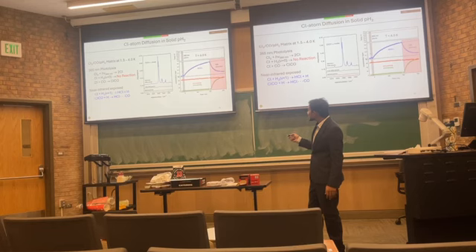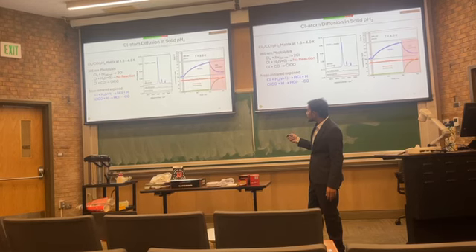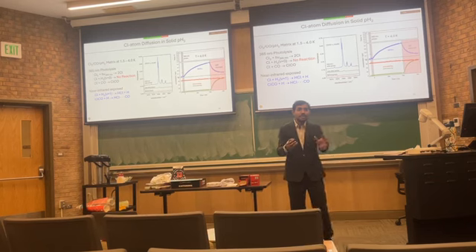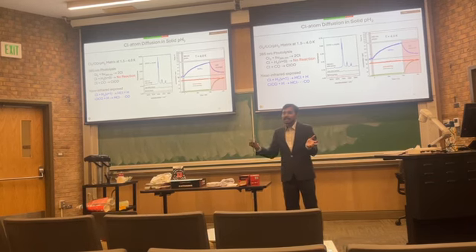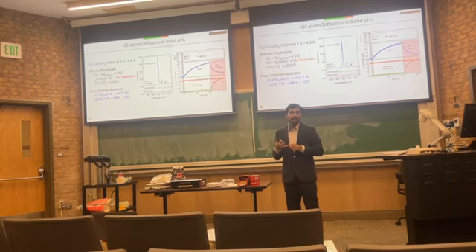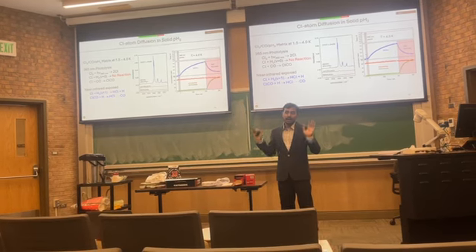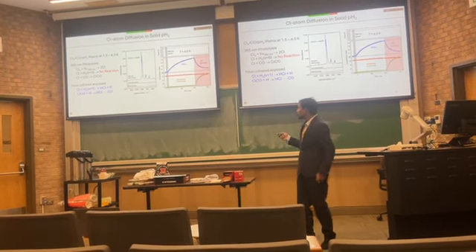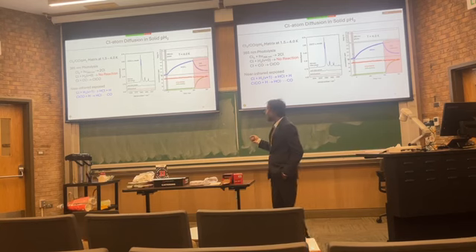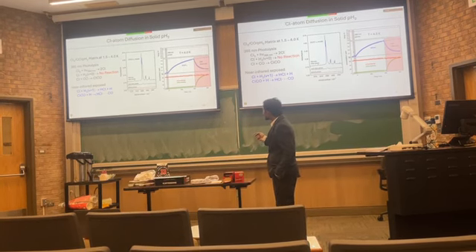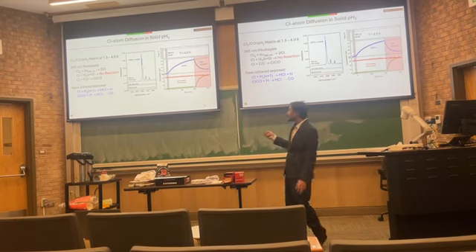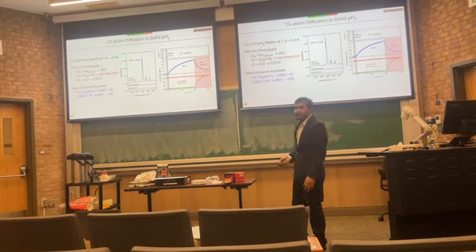Then if you look at ClCO, it was 0 before the photolysis. After photolysis, it grew over time from almost zero. So this is quantum diffusion, because a chlorine atom cannot move classically, since it's 35.5 times more massive than hydrogen. We don't expect any other way than quantum tunneling. So this is definitely quantum tunneling, these chlorine atoms diffusing and reaching carbon monoxide, making ClCO.